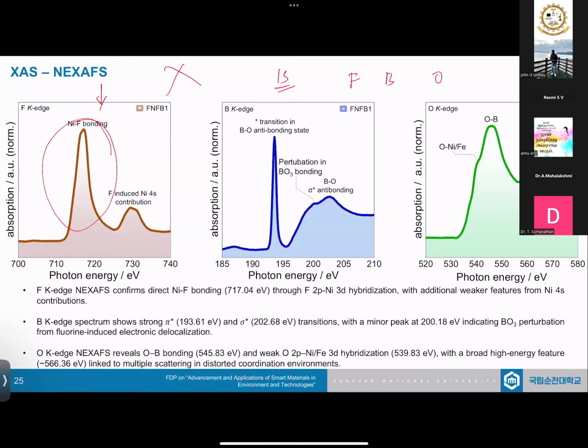The boron also was confirmed, and the small perturbation also confirms a slight alteration because of the fluorine inclusion. Also the O K-edge study confirmed the presence of the metal oxygen bonds: the pre-edge confirmed the metal oxygen bonds, and the main edge confirmed the boron oxygen bonds. So this was confirmed, and it completely satisfies our work.